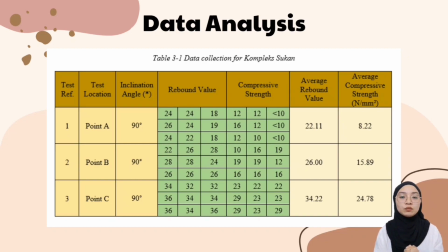As far as I can conclude based on the data collection, the average rebound value is between 20 to 40, which the quality of concrete is considered a fair and good layer. While average compressive strength can be seen in this slide, point A is 8.22 Newton per square millimeter, point B is 15.89 Newton per square millimeter, and point C is 24.78 Newton per square millimeter.